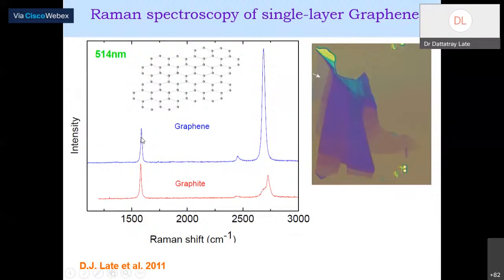There is a particular band which appears around 1580 inverse centimeter, or near 1600. This particular band appears because of the stretching of the carbon-carbon bond. Because this graphene layer consists of benzene rings, they are made of carbon-carbon bonds, and this appears because of the stretching of the carbon-carbon bond. So this particular band is known as the G band, or E2g mode. Then there is another band, which is known as the 2D band.